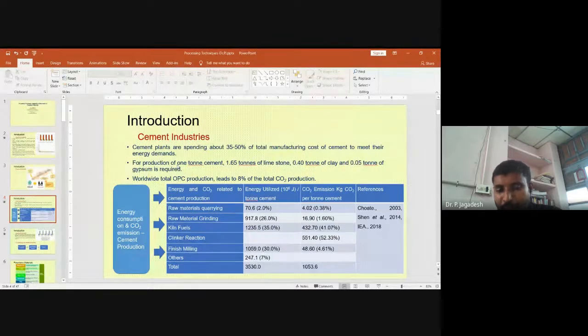If you come to carbon dioxide emission, quarrying is associated with less than 0.5%, whereas grinding accounts for 1.6%, and fuels account for 41%. Whereas the clinker reaction, which we call indirect emission of CO2, that is the decarbonation of your calcium carbonate and magnesium carbonate, emits almost 52.33%.